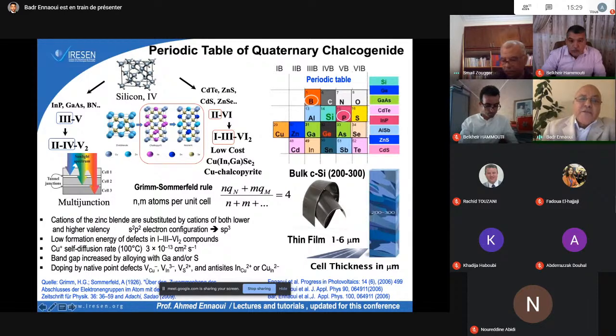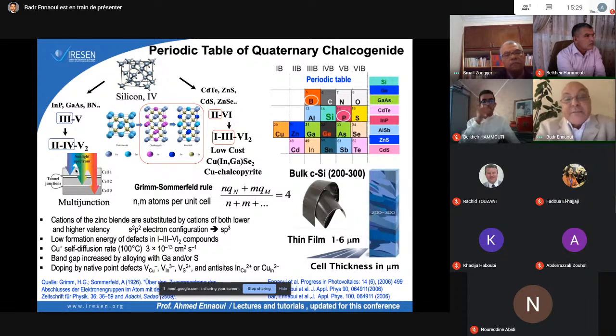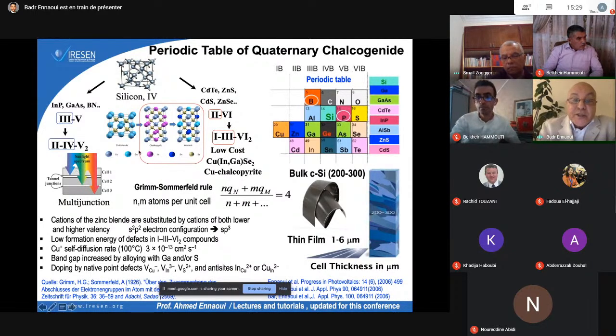However, if you go from silicon to 3-5 compounds or 2-4-5-2 compounds, the symmetry stays higher, and the doping for 3-5 compounds is very easy. You can just make a substitution. However, in the other kind, for cadmium telluride, zinc sulfide, zinc selenide, and copper indium gallium selenide, there is the compensation problem.